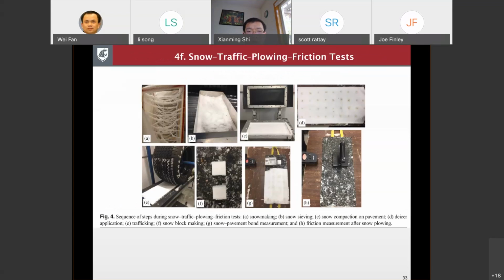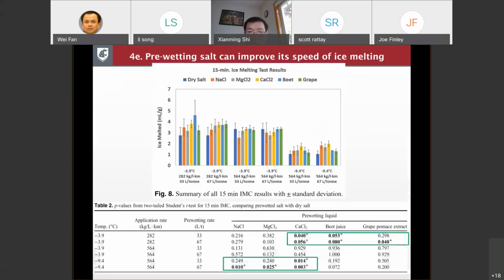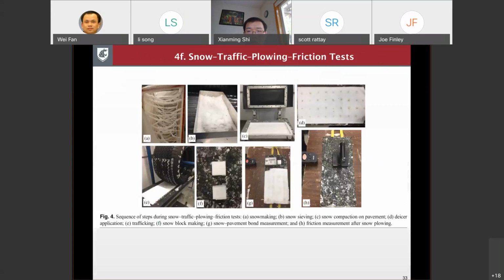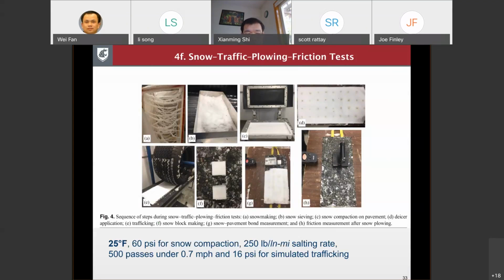Now, what about the other piece? Ice melting is one piece of the puzzle, but also in the field, we try to simulate the sequence of events in the lab. This is done at Montana State University. Basically we start from making our own snow, compact the snow, age the snow, and put down the pre-wet salt. As you can see, the amount is really small. Again, the salt is not intended to melt the entire amount of snow and ice. It's just intended to have the ice melting penetration and then undercut the bond.